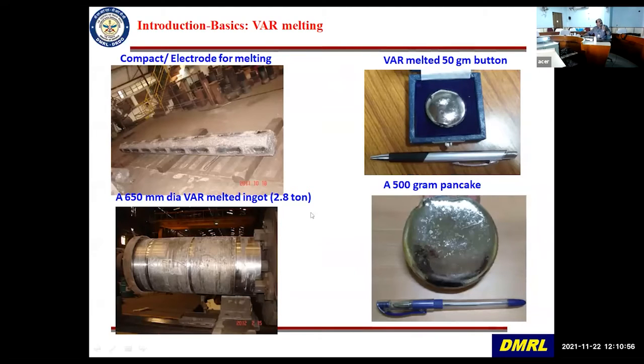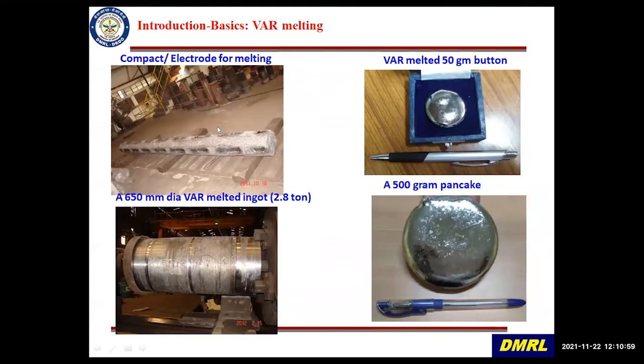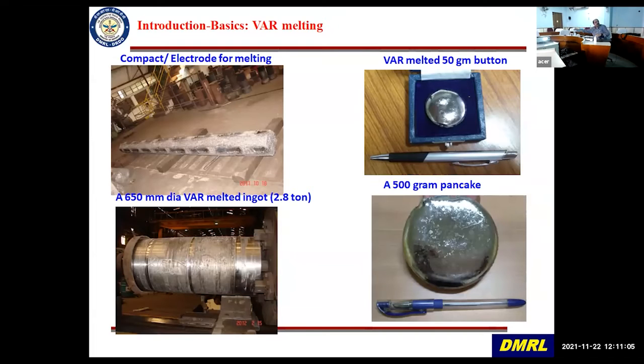On the top left hand side, you can see a compact which has been made. This is a 172 kg compact of an alloy that has been made and welded together. So this forms an electrode, and this is a melted ingot. So you can see it's a 650 mm dia ingot, 2.8 ton ingot. So this is the industrial scale melting, and in lab scale we can do 10 kg, 20 kg or whatever you want. And then this is a button which is melted in non-consumable electrode process, and also this pancake. This is around 100 mm dia and 7 to 8 mm in thickness.